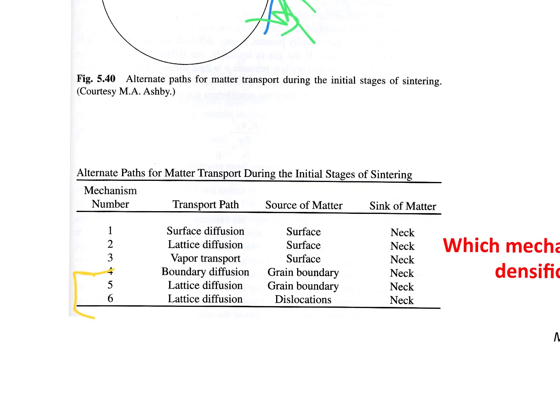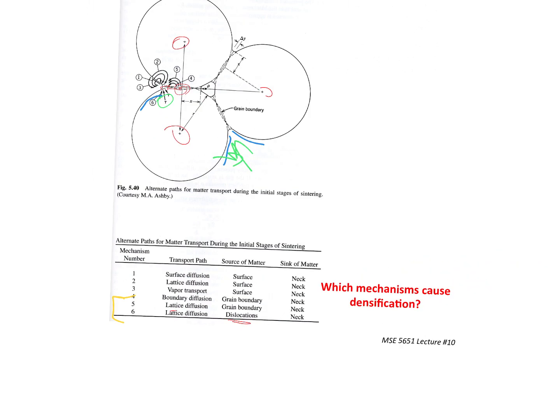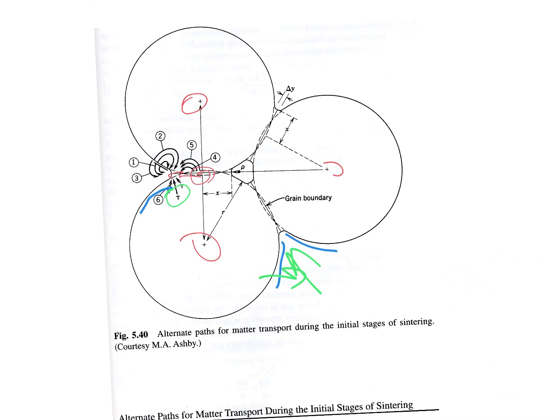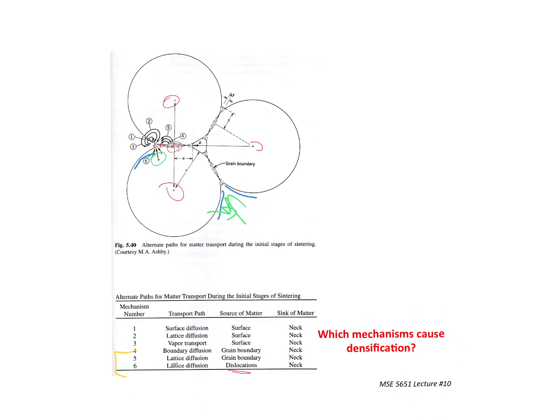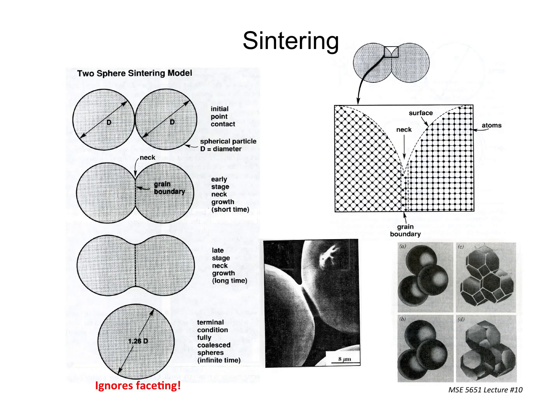And the same thing is true for lattice diffusion, because it's going from the grain boundary along the lattice, meaning the solid diffusion, volume diffusion, and going to the neck. And then we also have this weird one, dislocations, which also allow for transport toward the neck area and removing matter from the pathways in between those 2 crosshairs. Okay? Does that all make sense? So not everything that's going on in these systems is achieving our goals. It's achieving its goal, but it's not achieving our goal of trying to minimize the energy of the system.